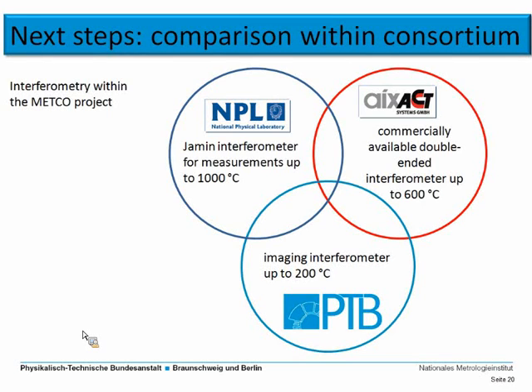And also our industry partner aixACT has upgraded their commercially available double-ended interferometer with a sample holder where they can reach temperatures up to 600 degrees centigrade. So we have quite a bit of overlap between those three systems. And if we measure the same samples, we should be able to compare our results, which should be interesting to see what comes out of this kind of comparison. So this is what we're going to do within the next month.